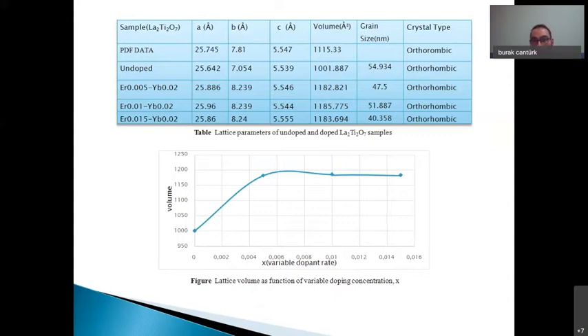But the most significant point to be made is that a detailed examination of the peaks reveals the presence of slight shifts in the peak position to each side, left and right, with the increase of doping concentration. These shifts were noticed during the calculation of lattice parameters and the volume of the unit cell, as we can see from the tables and figures.